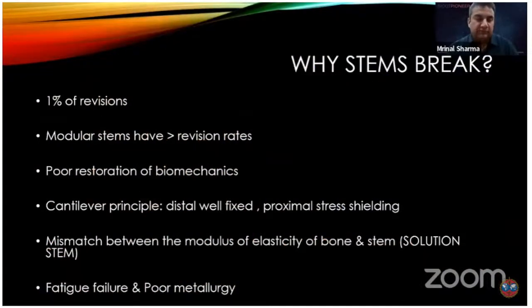So why do stems break? Stem breakage is the indication for revision in almost 1% of cases, and modular stems break even more, with up to 4% of revision surgeries done due to breakage of modular stems. Now, there are many reasons for stems to break. It can be poor restoration of the biomechanics, the cantilever principle working with a well-fixed distal stem and proximal stress shielding, and mismatch between the moduli of elasticity of bone and the stem, especially some stems like the Solution stem, which break very often. Fatigue failure, poor metallurgy, and a lot of modularity all contribute to stem failures.